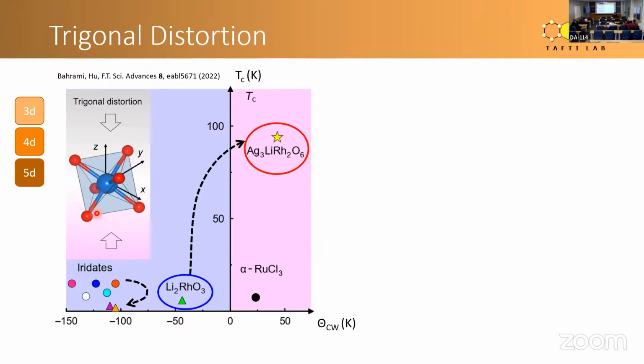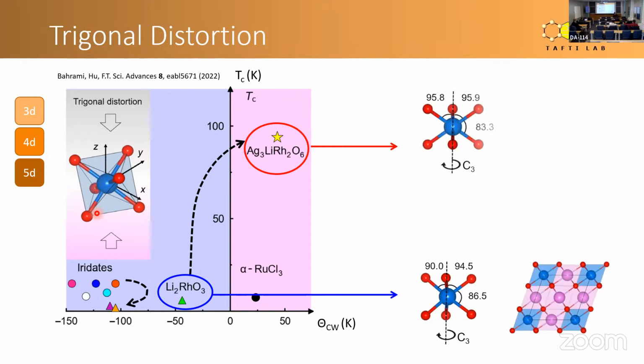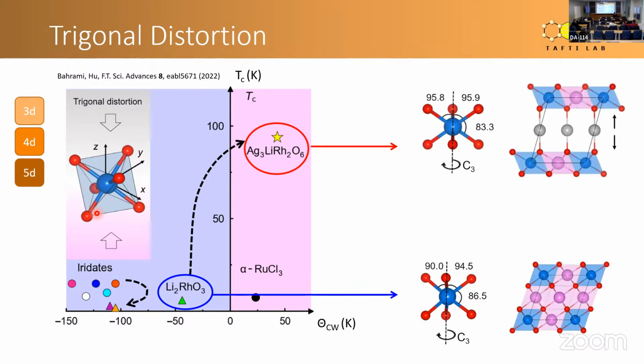And therefore, you can trigonally either compress or stretch each octahedral unit. And it so happens that in lithium rhodate and silver lithium rhodate, you have quite different degrees of this trigonal distortion. We performed crystallographic analysis of lithium rhodate and silver lithium rhodate, and mapped and basically found all the bond angles between oxygen, rhodium, and oxygen in both compounds.